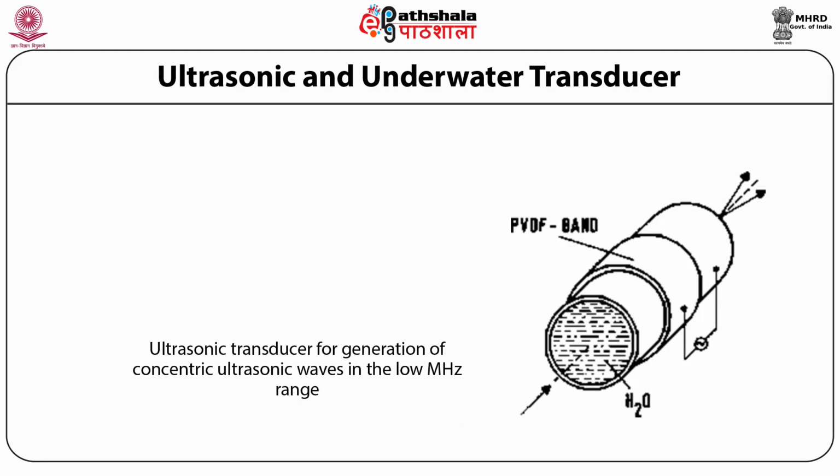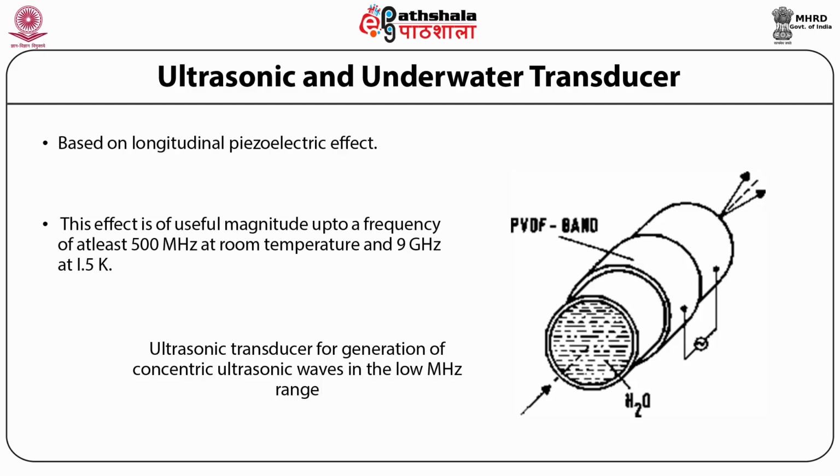Ultrasonic and underwater transducers. Ultrasonic and underwater applications of the piezoelectric materials are based on the longitudinal piezoelectric effect. The effect is of useful magnitude up to a frequency of at least 500 MHz at room temperature and 9 GHz at 1.5 Kelvin.